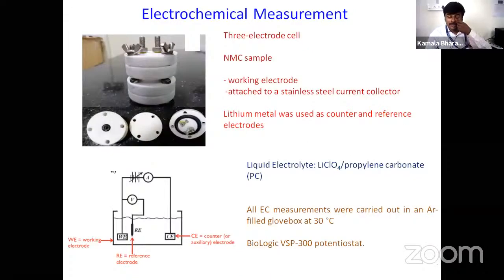So how do we do electrochemical measurement? We use a 3 electrode setup. We have a homemade setup. Also, we use coin cell. In 3 electrode, basically you have a working electrode, which is our thin film, and for reference and counter electrode, we use lithium foil. So what we do is we perturb the system using working and reference electrode and measure the response between working and counter electrode. That means apply voltage and measure the current.